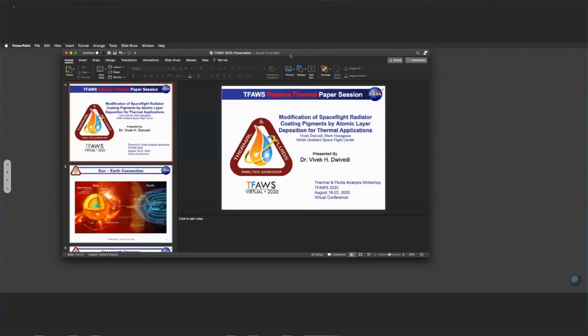The other thing that we utilize is a very simple tape test, where we will coat, say, ITO or another material on a glass slide or a silicon wafer, go through surface analysis, and do a very simple tape test to see if we have any removal of material. And going through that process, what we found is that the ITO is very robust, even through day-to-day handling of the material.